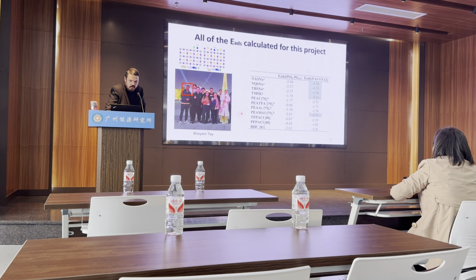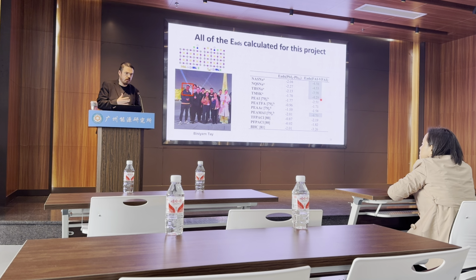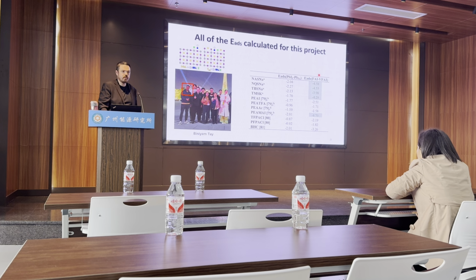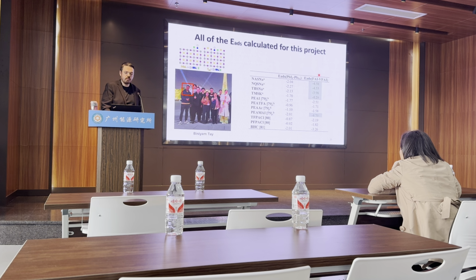So you can see that the sulfonates actually passivate perovskite much better than the amines. So that's interesting. They bind stronger, but there's probably some kind of threshold above which we need binding strength. So excessive binding strength might not necessarily be a good thing. Just because it's stronger doesn't mean it's better. So that's just something to keep in mind.